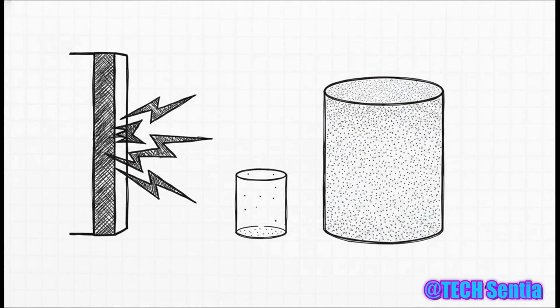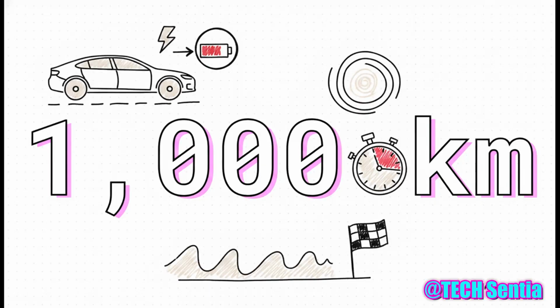And that insane safety leap brings us to what scientists call the golden combination. The logic has always been that a rigid, solid electrolyte layer could act like a physical wall to stop those jagged dendrites from growing. Stop the dendrites, and you can finally, safely, ditch the graphite and use a pure lithium metal anode. Why is that such a big deal? Because pure lithium metal can hold roughly 10 times more lithium ions in the exact same space compared to a graphite structure. That tenfold jump in ion storage translates into some absolutely mind-bending real-world numbers.